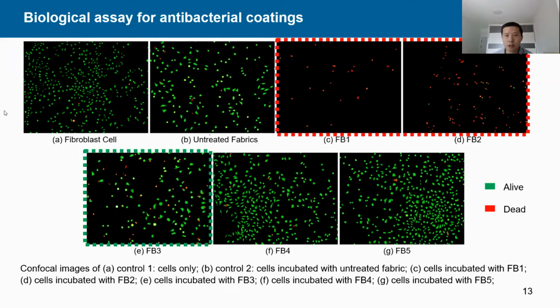Cytotoxicity was studied through confocal images, which, as we see here, show live cells, where the number of live cells can indicate the viability of cells. As you see here, we have 5 samples, incubated with murine fibroblast cells, and there are two control samples, A and B. The cells were incubated on the standard protocol using unexposed medium in order to follow the growth of cells, and cells incubated with untreated PET fabrics under the same condition.